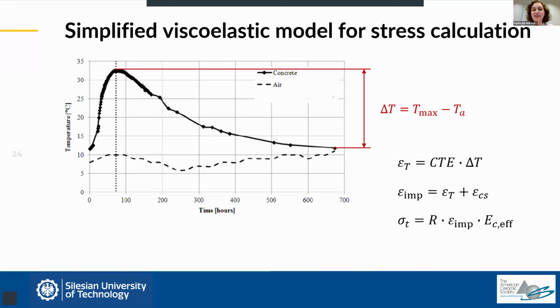If we add to this the effect of shrinkage, like drying shrinkage and autogenous shrinkage, this is how we obtain the total imposed deformation. And as I said, only the restrained part of this deformation is responsible for producing stress. So for the calculation of stress, we only take this R times epsilon, which means the degree of restraint times total imposed deformation. And we use a linearization technique.